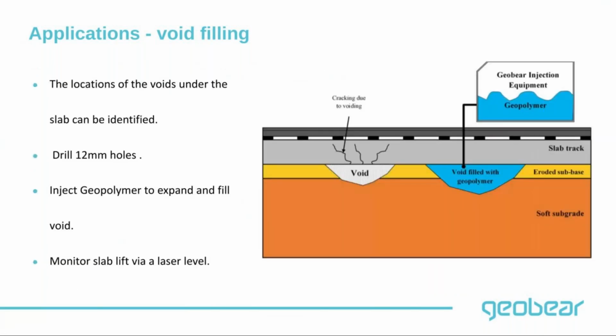We can identify the locations of these voids and drill to these voids via a 12 millimeter diameter hole, and start filling the geopolymer in these voids. As soon as the geopolymer gets into the void, it will start expanding and filling that void. When the void becomes completely filled, the slab track could start to lift, and this is quite good because it can help us restore the track geometry to the original design. As we inject, we can keep an eye on the levels of the slab and make sure that we get our construction tolerances to the millimeter.